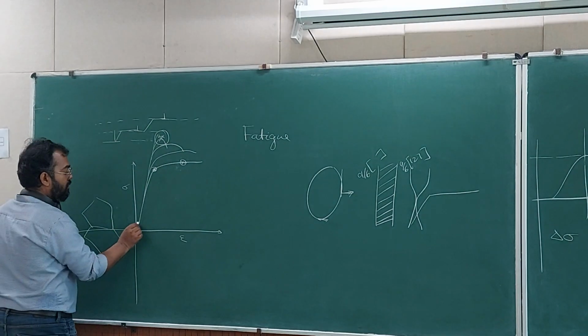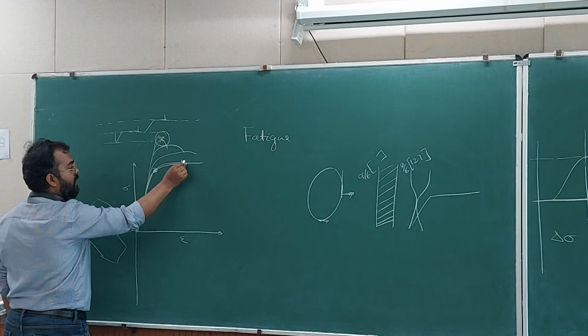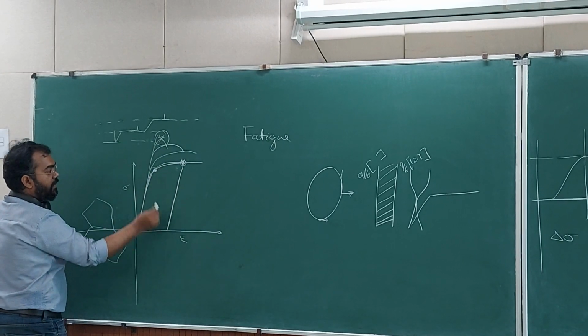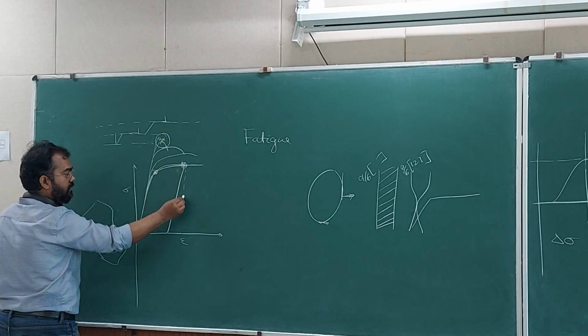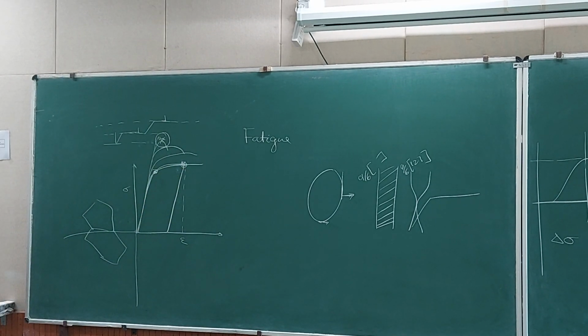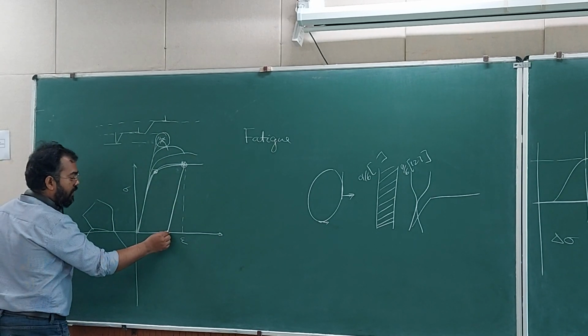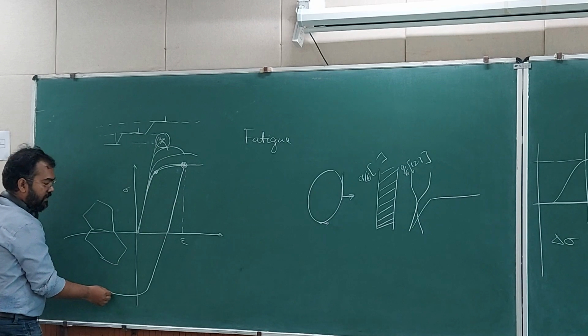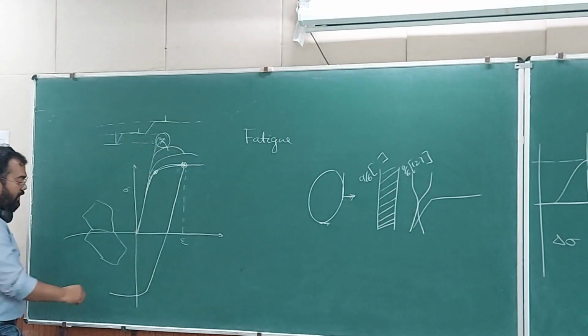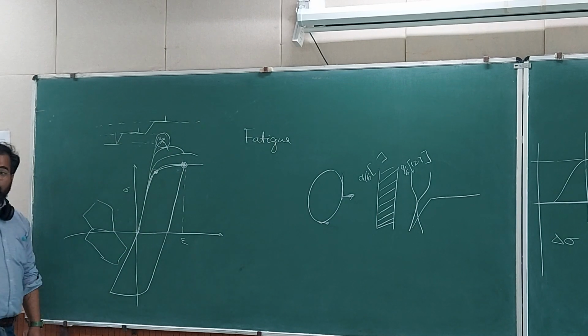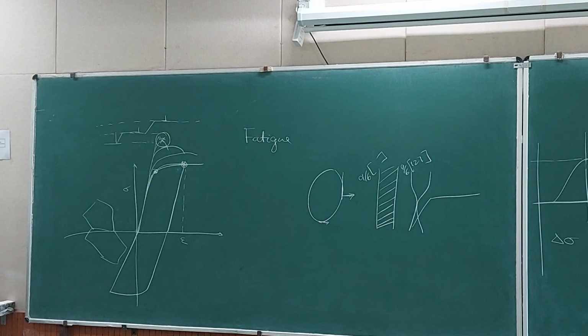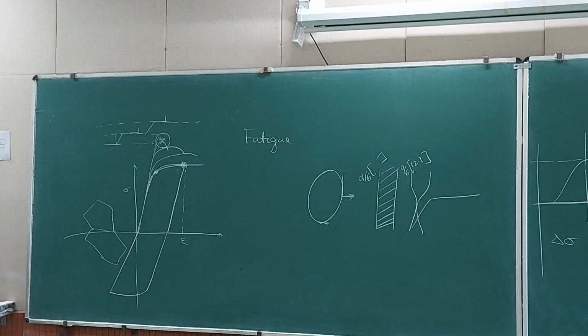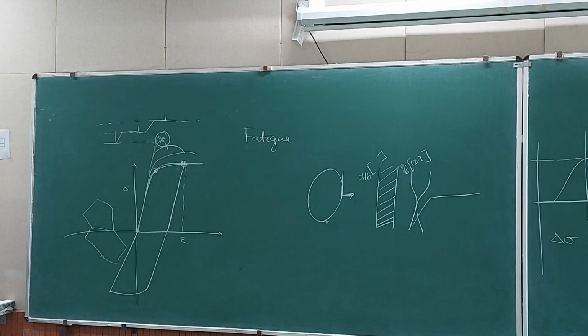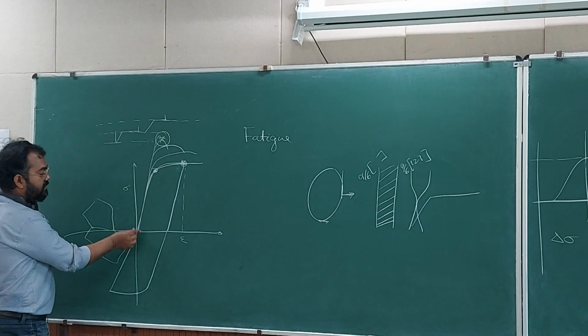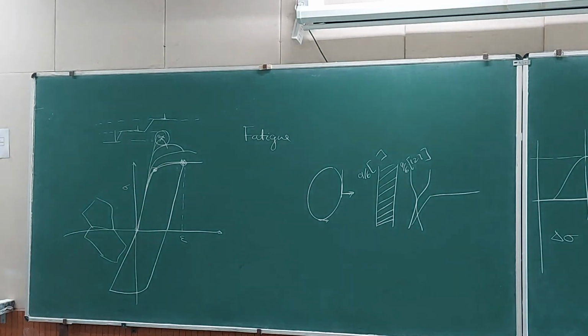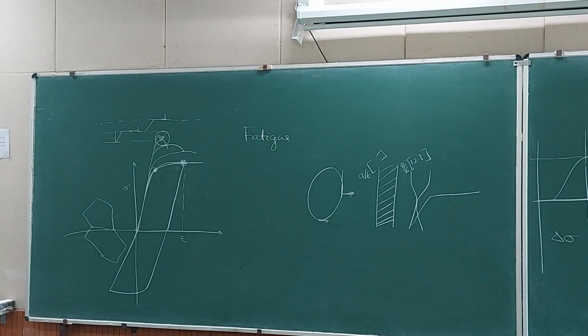So you go and load it to sigma max, and then you unload it. Because it is higher than yield strength, you will have some amount of strain which will recover with unloading, and then you are loading it again in the reverse direction, and yielding will start, and then you will unload it. It should come back to the same point. It will not, because of the Bauschinger effect, because of adiabatic heating, it will not come to the same point, and then you will have a hysteresis loop. That is the amount of heat which is generated per unit cycle in the system.